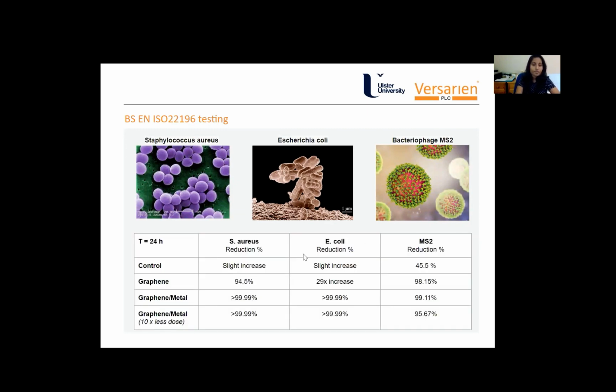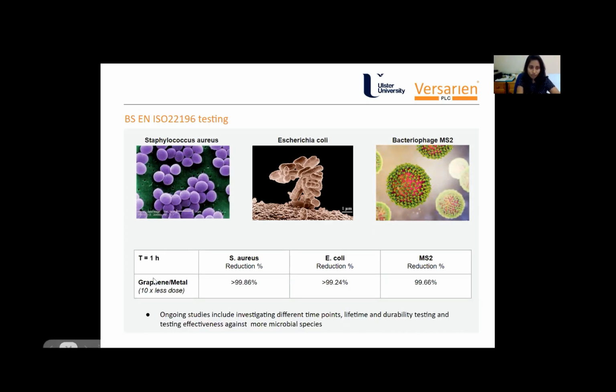Here you can see the results. Both our graphene and graphene-metal hybrid show a significant reduction of colony forming units, except E. coli on graphene, which we will discuss later in the slides. And these are our 24-hour results. In order to test the effectiveness of the active ingredient, we diluted it, or decreased the dosing, 10 times, but still you can see 99.99%, that means a 4 log reduction, in both of these bacterial strains. We also reduced the test time from 24 hours to 1 hour with 10 times less dosing, and still you can see a 2 log reduction. The next stages of this study include testing the life cycle and durability of the coating, and testing the effectiveness against a wide variety of microbial species.